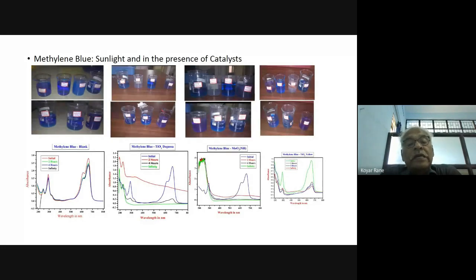We have been working at the laboratory level on how to break the organic molecules. Normally people use methylene blue as a target material, as a model material. And methylene blue as such, if it is exposed to sunlight, hardly degrades. You can see here, even at 24 hours, there is not much degradation taking place. The moment you put some metallic catalyst, you can see the degradation taking place almost 80% to 90%. Various catalysts can be used, and the degradation can be done by adding different catalysts, for example, titanium oxide, molybdenum oxide, and so on.